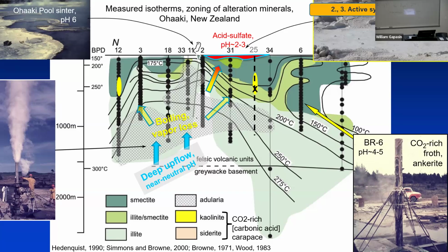A machinist made a sealed downhole bottle. We sampled this, brought it up, and let go the pressure into a sodium hydroxide solution. For 20 minutes, we bubbled CO2 into the solution. It was over 1.5 molar, converts to about pH 4.5, or say a 5% CO2 solution. That was the cause of that casing break. And thus, that was the reason that we recognized these CO2-rich fluids responsible for the casing corrosion.